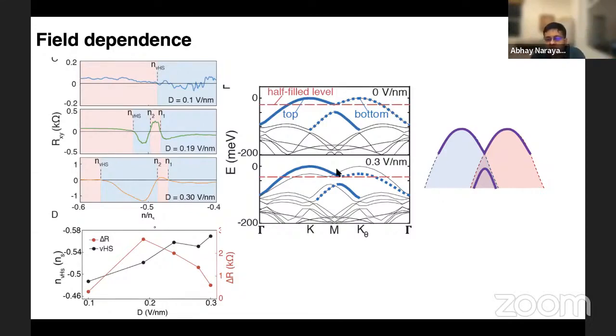And so this you can see here, this is once again the DFT calculation done at 0 electric field and done at some non-zero electric field. As you start to apply this electric field, you see that these 2 originally degenerate valence bands now start to displace from each other. And so effectively, you can tune the band structure and the bandwidth by applying an electric field. So the electric field tunes the bandwidth of the system.